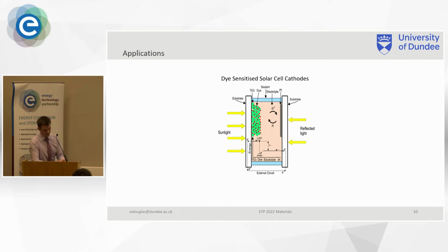So there's a few things that I'm looking at with the platinum in terms of the thickness, how the thickness will affect this reaction, and also the porosity. As we saw in the previous slide, as we increase the porosity, we reduce the conductivity, but we could also potentially increase the reaction rate with the electrolyte. So it's an interesting thing that I'm going to be having a look at.